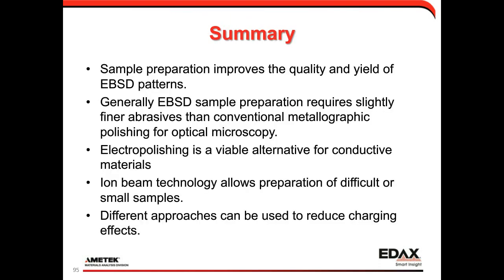So with that, I'd just like to summarize what we've talked about today. First, sample preparation improves the quality and the yield of EBSD patterns. Generally, EBSD sample preparation requires slightly smaller and finer abrasives than conventional metallographic polishing. Metallographic or mechanical polishing can be used to prepare quite a number of samples. Electropolishing is a viable alternative. Ion beam technology allows preparation of difficult or small samples, and there are a couple of different approaches we can use to reduce charging effects.